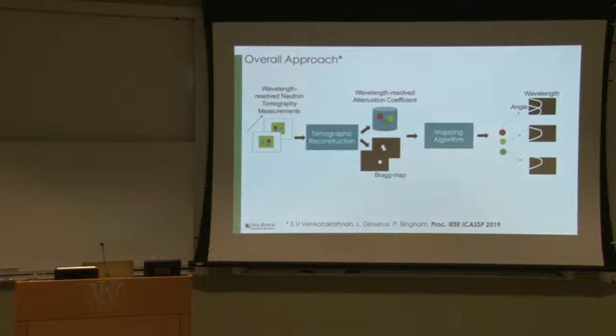So the main idea that we've come up with is to say that we can do a reconstruction out of it. So the main challenge would be to go back to the data sets and look at regions which contain these single crystal, I would call them, mismatches. So this is something that's unexpected, that the attenuation suddenly changed and it resulted in the measurement changing in a certain way. So if you can design a method that can find out those regions which were due to Bragg scatter, you can kind of leave them out and do a reconstruction and also find a map of the actual data which you didn't use or you threw out because of Bragg scatter. And then you can design a mapping algorithm after that to get some extra information. So along with the CT scan, you can get some information about how each of these domains changed as a function of angle. You can get some crystallographic signature. So that is our proposed idea.